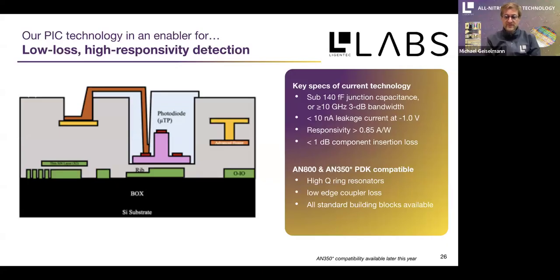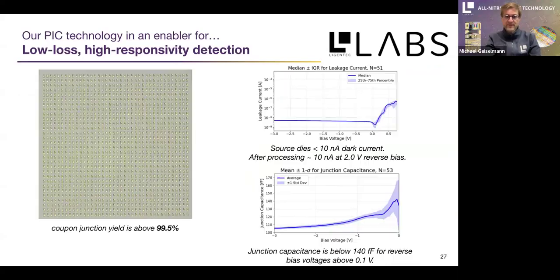You can use all the PDK components that are developed in the nitride process, which is shown here in the green. So the green waveguide is the nitride, and then with this local cladding opening, we integrate the photodetector onto the wafer, and through evanescent coupling of the waveguide to the photodetector, we detect the light on the PD. And here is an image of the coupon.